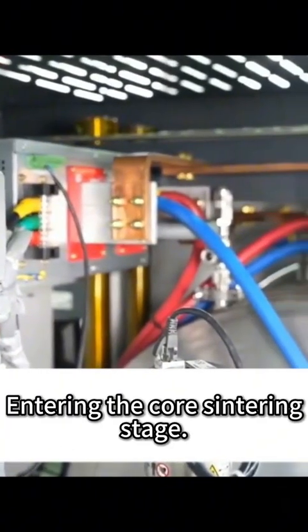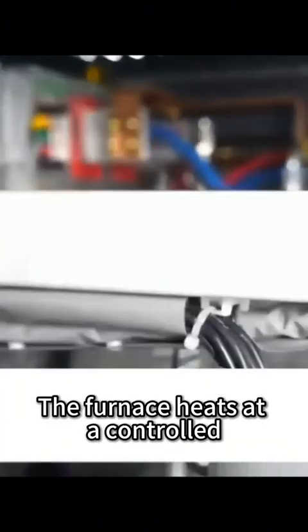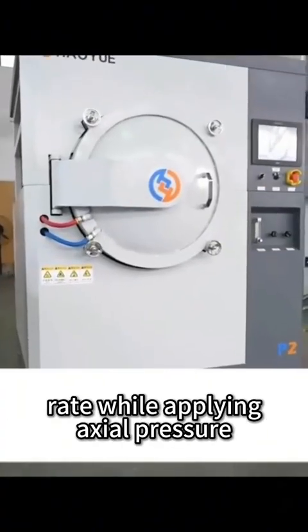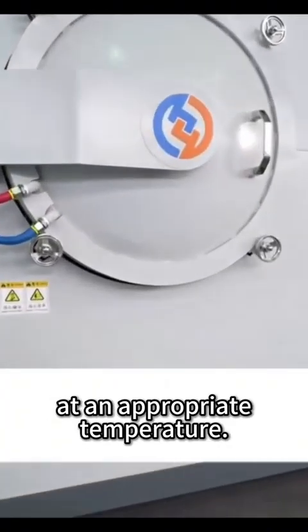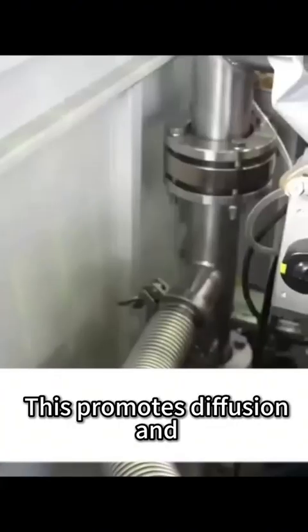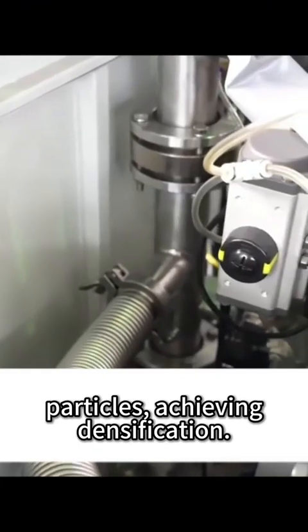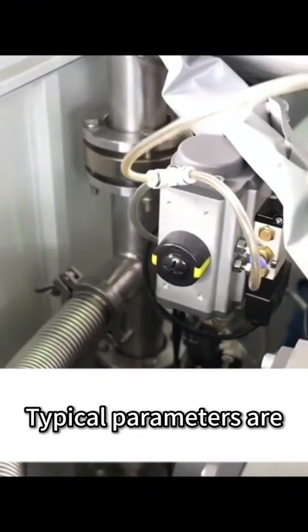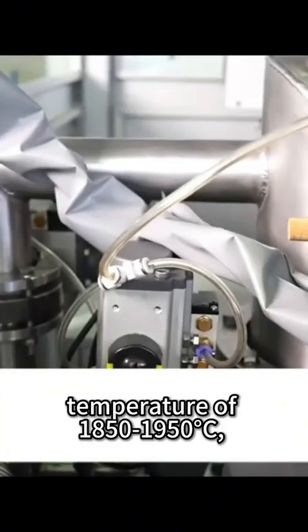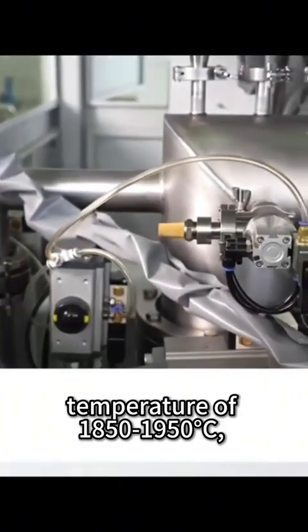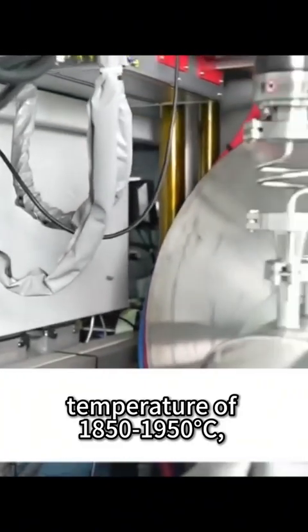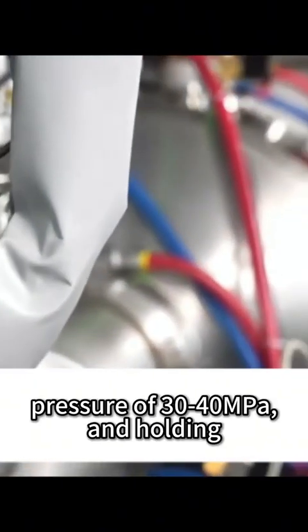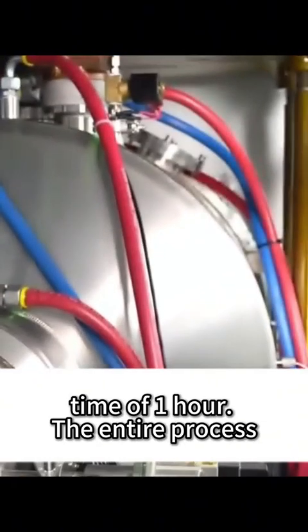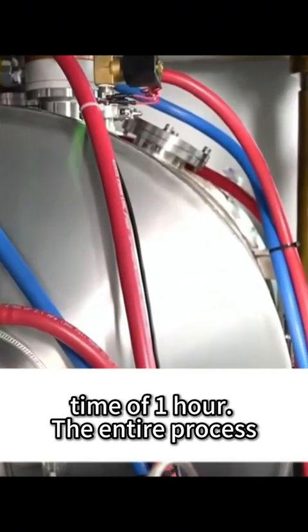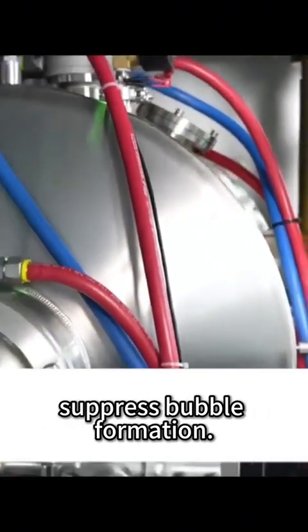Entering the core sintering stage, the furnace heats at a controlled rate while applying axial pressure at an appropriate temperature. This promotes diffusion and bonding between powder particles, achieving densification. Typical parameters are a temperature of 1850-1950 degrees Celsius, pressure of 30-40 MPa, and holding time of 1 hour. The entire process is carried out under vacuum to suppress bubble formation.